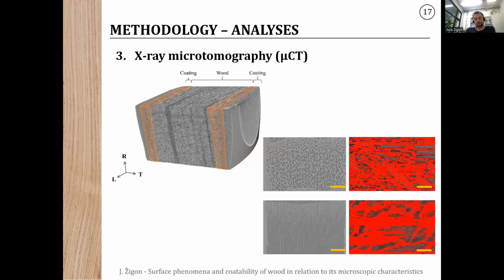So after modeling the scanned samples, we can see on the left side the image of such a sample. We were focusing on the interface between the coating film and the substrate, and on the right below, how we were, let's say, distinguishing between the coating and the wood. I can say it's quite challenging. We can use some elements which could be added into the coating to get better contrast between the coating and wood.